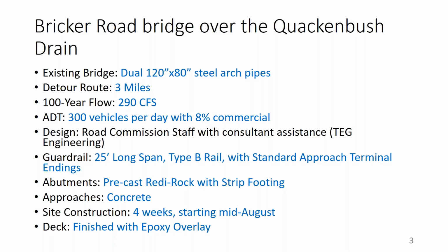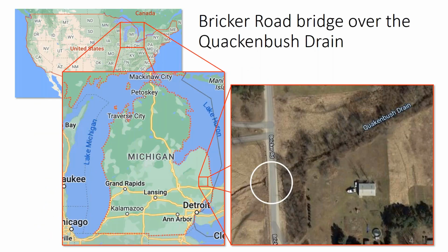We also used the precast Redi-Rock blocks with a strip footing. Again, ABC. Approaches were concrete. We had to wait for those to cure. It wasn't ABC. Ultimately, the construction took about 4 weeks. We had a holiday in there too, so we had a week or so off to let the concrete cure, so that worked around the holidays. In the end, we finished off the bridge with the epoxy overlay over the whole thing.